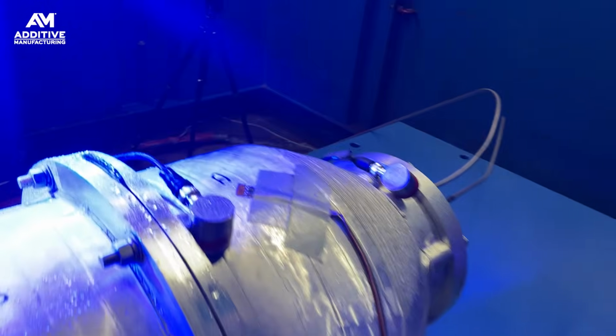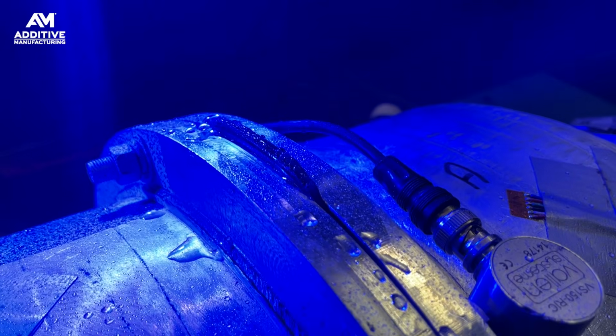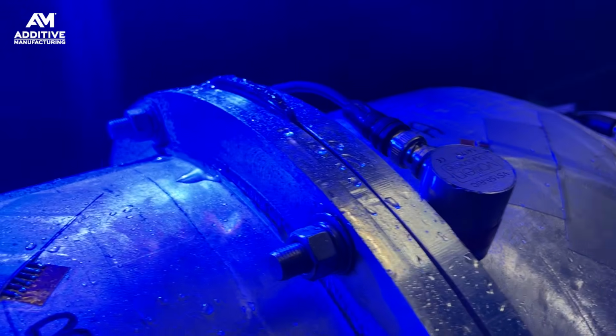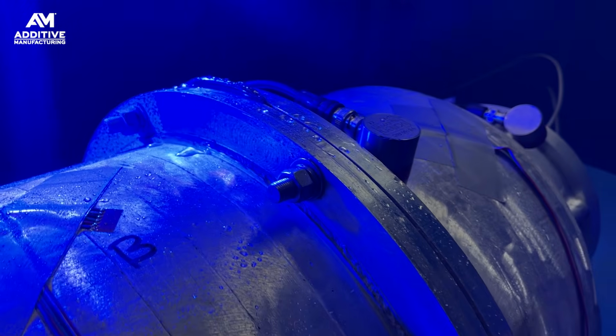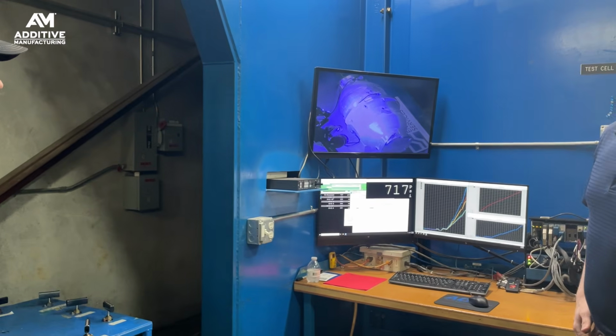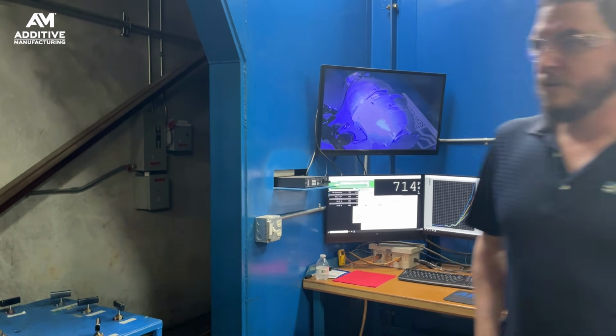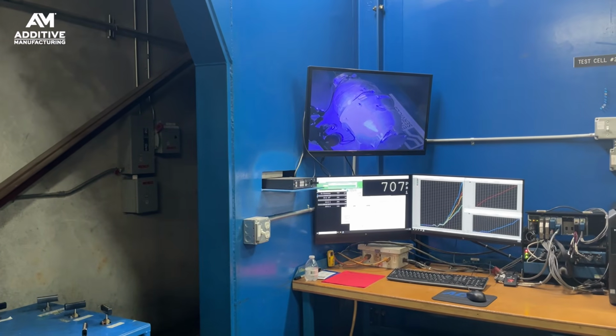Digital image correlation turned out to be the tool that showed the failure in the part before anything else, partly because it didn't fail as expected. We were monitoring all those during the test and it ended up leaking at a flange that had an O-ring seal. So since this part was not originally designed to undergo internal pressure, but mainly external pressure, that flange is a weak point for this type of loading condition. But it was good in that we saw that the additive material was able to withstand the internal pressure even after the fatigue cycling and did not fail. It was another non-additive part that was the leakage point. The 3D printed pressure vessel was holding above 700 psi when the O-ring failed and the flange started to leak.